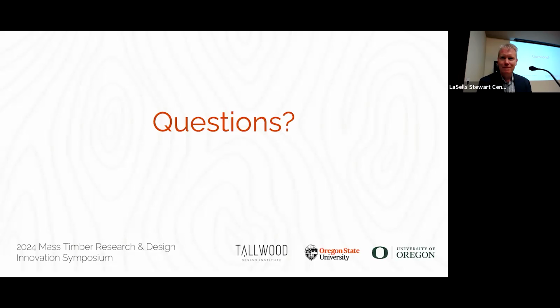Good question. Now I can hear it, okay. That's a good question. So we purposely did not use a membrane. We cast concrete directly on the CLT, which also means to start your creep test, you have to wait until everything has reached equilibrium. The concrete has to cure, and not just 28-day strength, it's got to reach its plateau strength. Otherwise, your stiffness is constantly changing because your material properties are changing. And then the moisture content in the wood has to reach equilibrium as well.